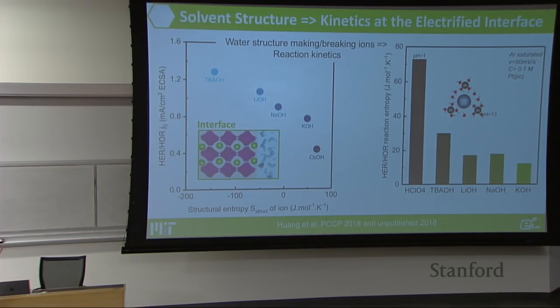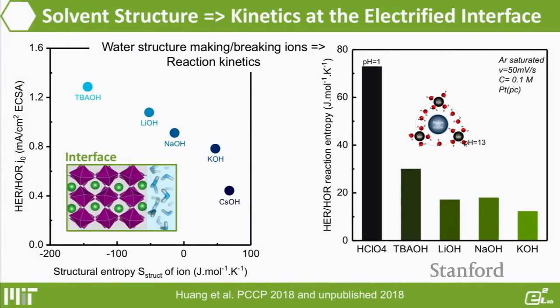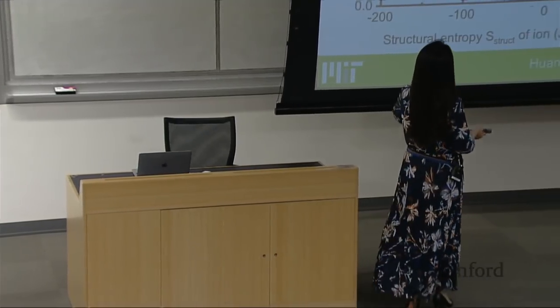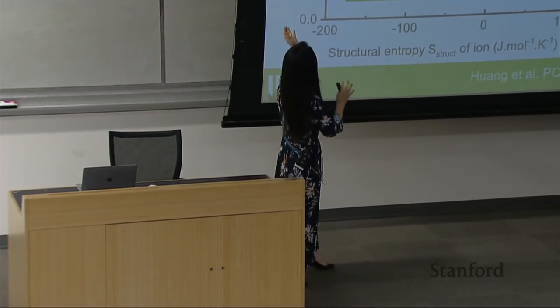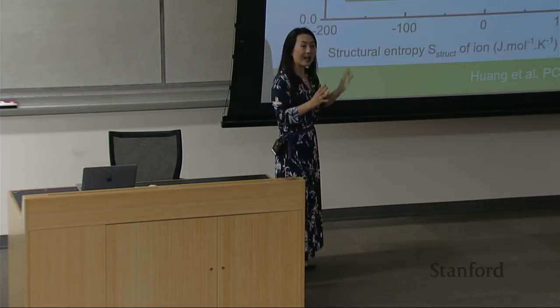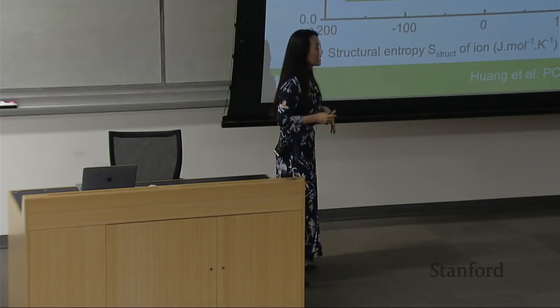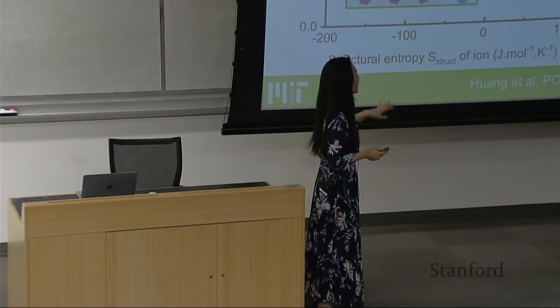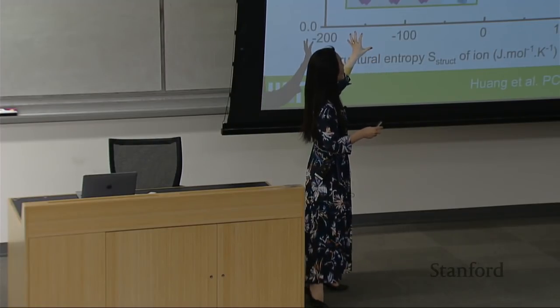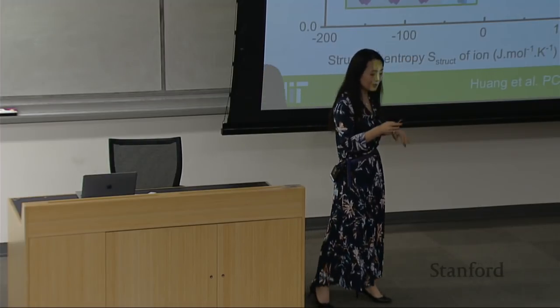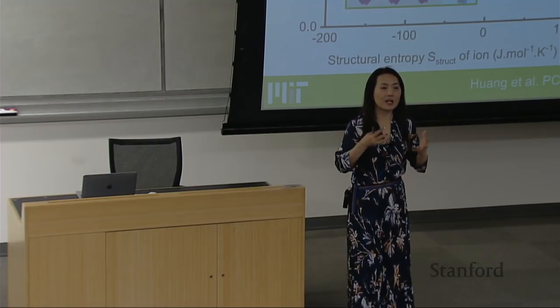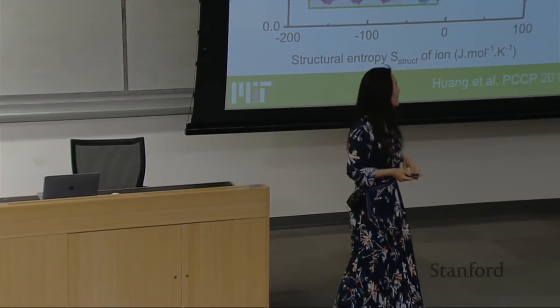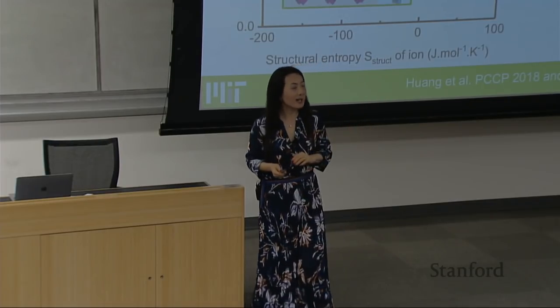So I want to end by saying that so far we've been discussing manipulating the electronic structure, or phonon structure, of solids. And in the past 5 years we've been doing quite a bit on the chemical physics of liquids. So this is one example with the same reaction, the reaction of hydrogen evolution. If you change the cations in the solution, you can change the reaction kinetics by many orders of magnitude. So without changing the reaction, but changing the water structure, you can change the reaction kinetics. And we believe that has to do with influencing the entropy change of such half-cell reactions. So this is one area that we're going into.